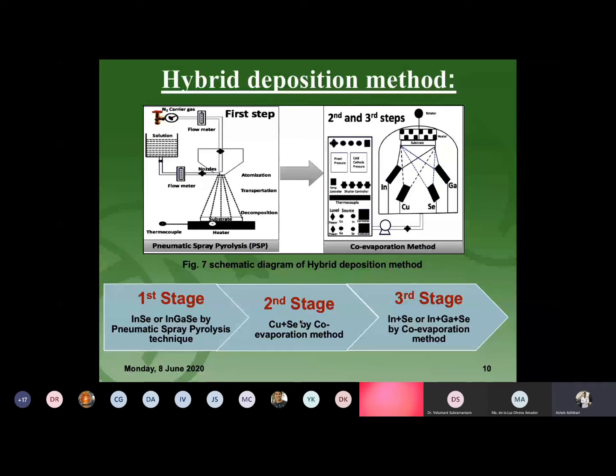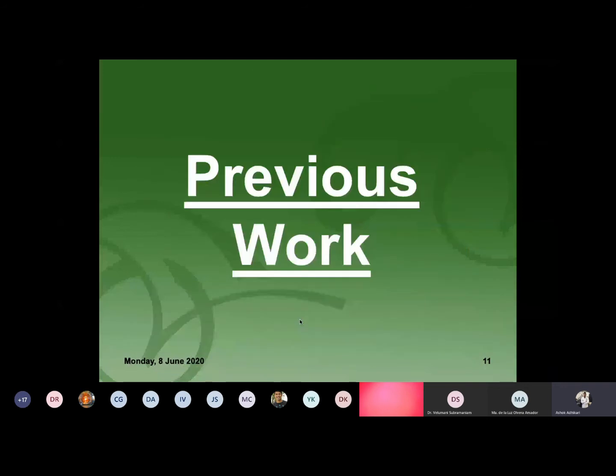Previously, I presented the work on indium selenide by pneumatic spray pyrolysis, and also optimized the better conditions to obtain the gamma indium selenide phase, which is normally used for the precursor layer for the synthesis of the absorber layer.